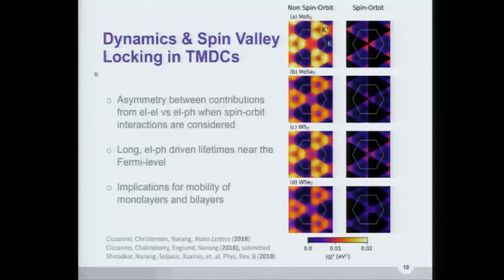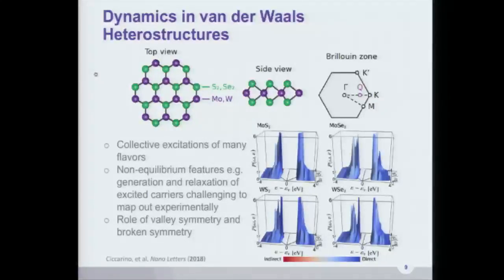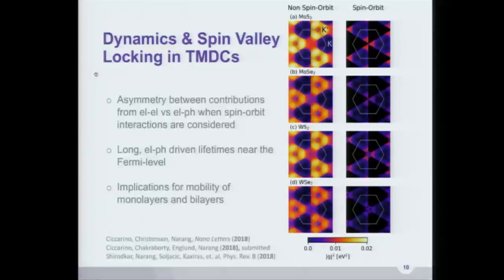I've been talking about electron-phonon times to you for the past few slides. An approximation in the field prior to our work was that you can get the electronic states, but not include the spin-orbit coupling in the phonon calculation. If you think of the moly or tungsten-based compounds, particularly tungsten, you expect it's heavy, right? Tungsten selenide is heavy, should have pretty high spin-orbit coupling. If it has a bunch of spin-orbit coupling, this should be included. Most people included it in the band structure, but did not include it in their calculation of the electron-phonon coupling. And you would say, OK, well, maybe that's a small correction.